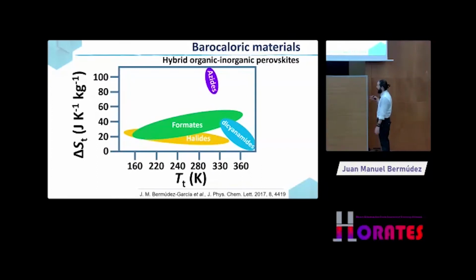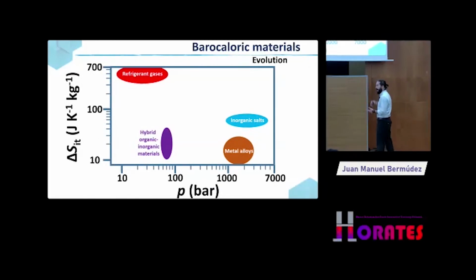We found that within all these families, the most interesting family of materials would be that of azide perovskites, because they work near room temperature and they exhibited thermal entropy changes, induced with temperature, of about 100 joules per Kelvin per kilogram, which was very large in comparison with the previous barocaloric compounds. So we tested some of these azides, and other groups in parallel started to study hybrid organic-inorganic materials for barocaloric purposes. And we really did find that the entropy change induced by pressure increased, at the expense of applying more pressure.